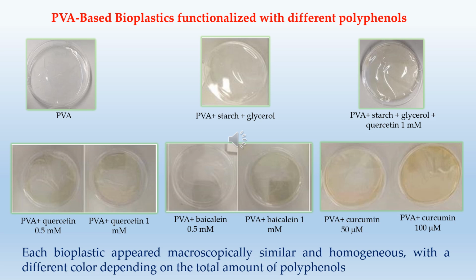Each bioplastic appeared macroscopically similar and homogeneous, with a different color depending on the total amount of polyphenol. At this point, the analysis of their functional and biological characteristics was performed. Unfortunately, already from the first tests carried out it emerged that bioplastics containing starch and glycerol were not suitable for our research purposes. So we abandoned their use and continued experiments with bioplastics containing only PVA and polyphenol.